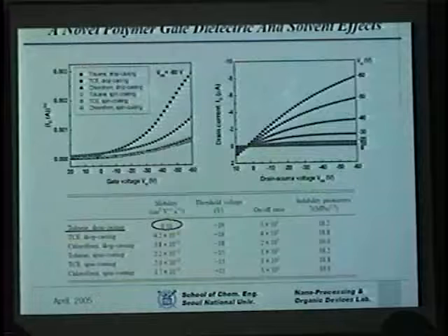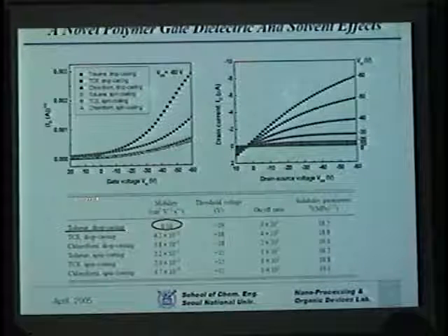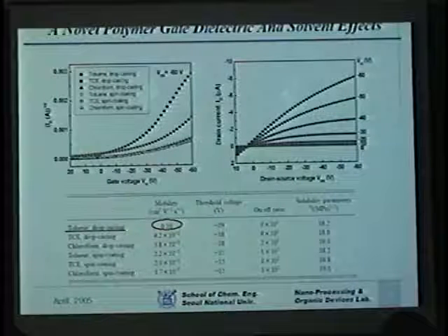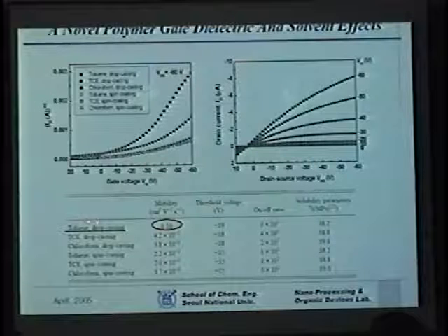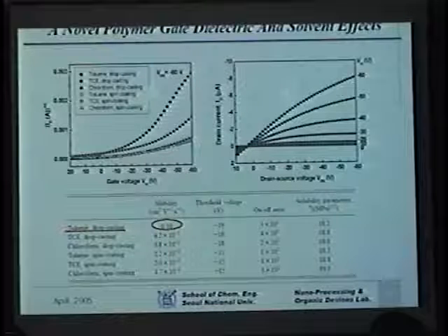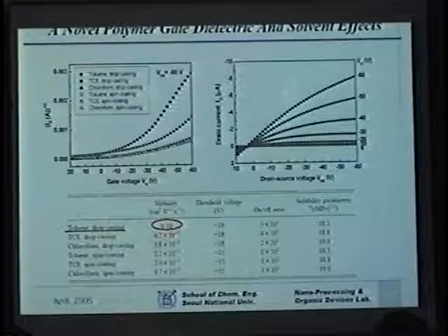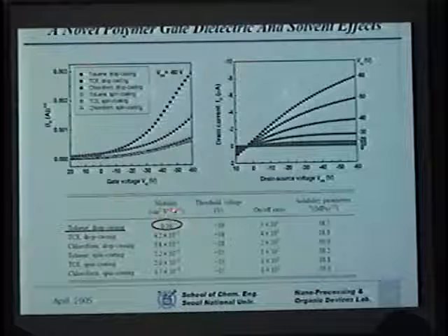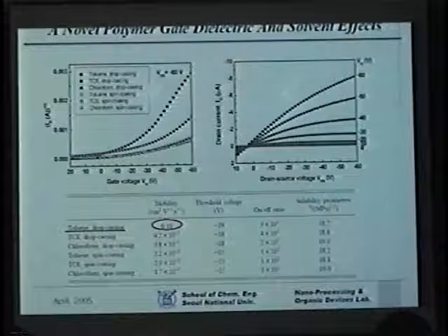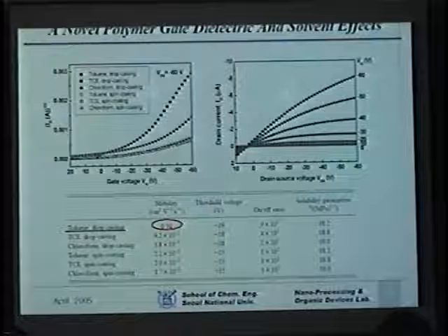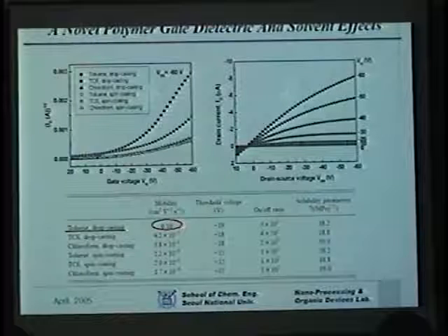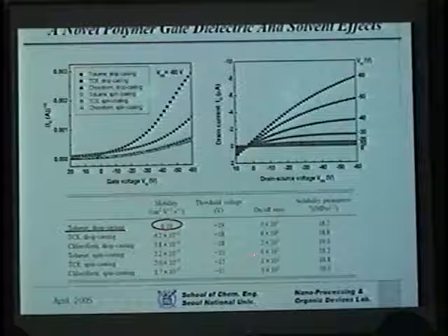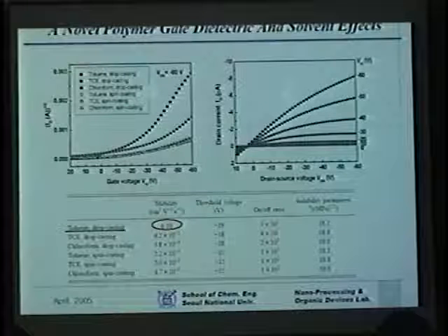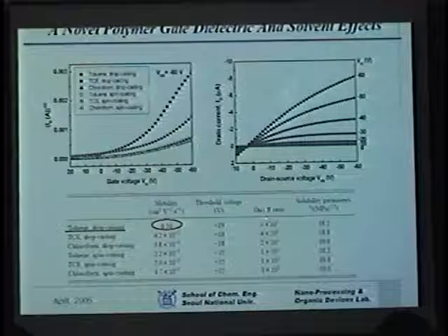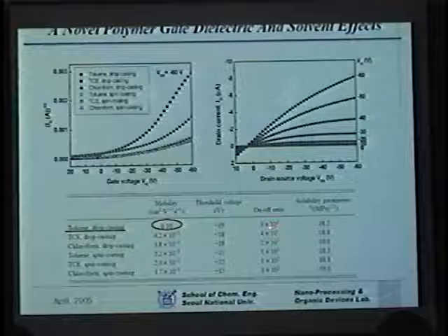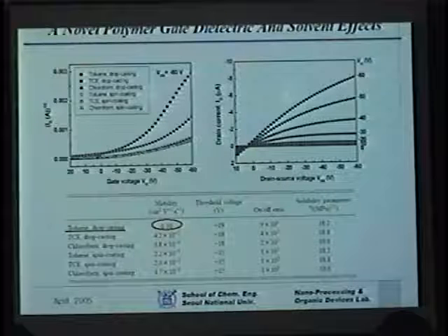And you can see that when you do the toluene drop casting, you can get the highest mobility ever reported in the literature. That is, with a polymer gate dielectric and polymer semiconductor, this is perhaps the highest mobility ever reported. However, as is typical with a polymer dielectric and polymer semiconductor, the on-off ratio is fairly low.